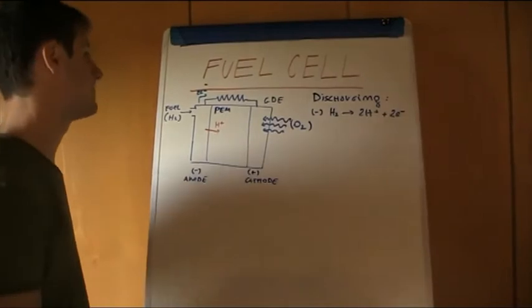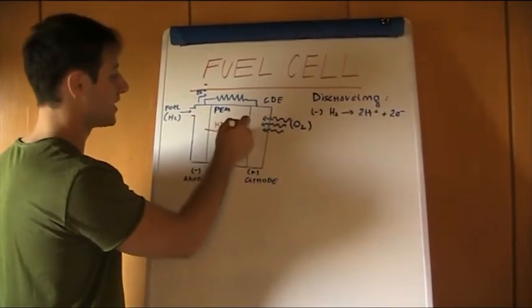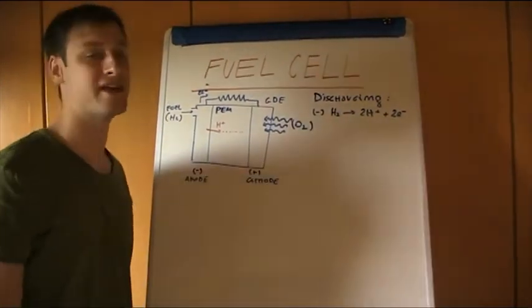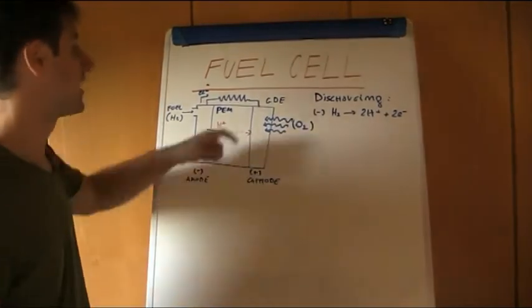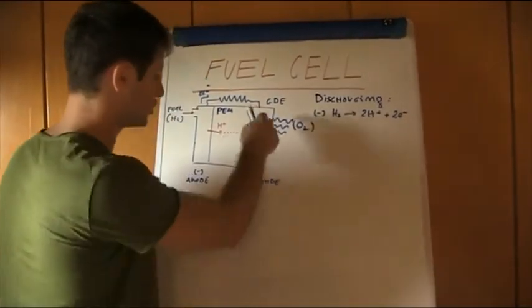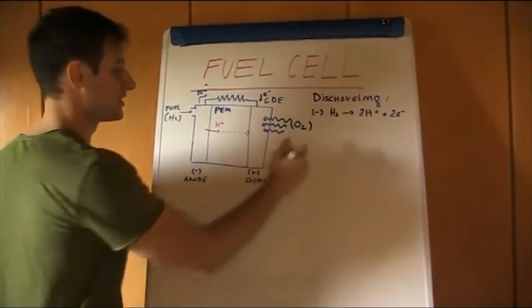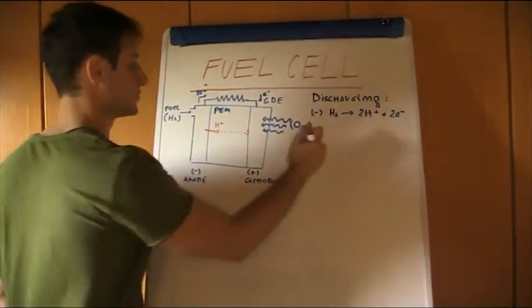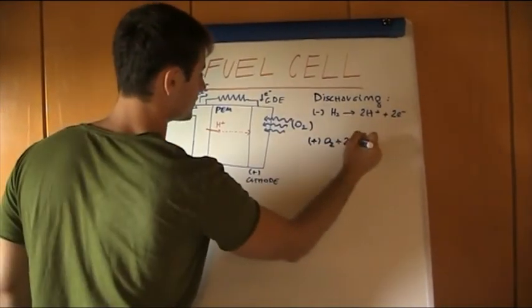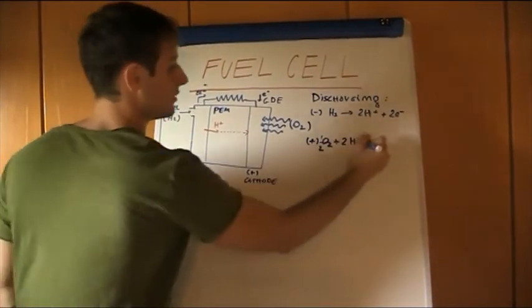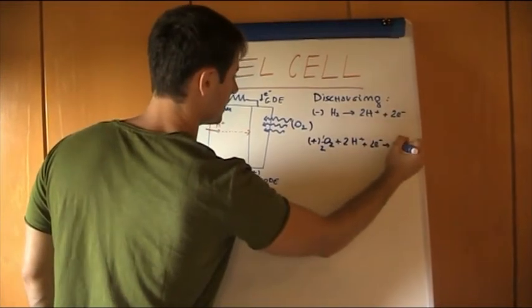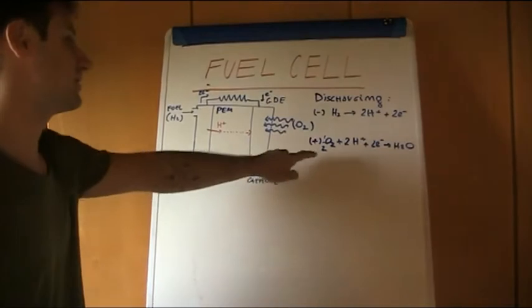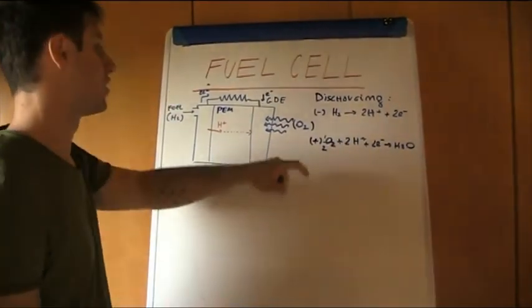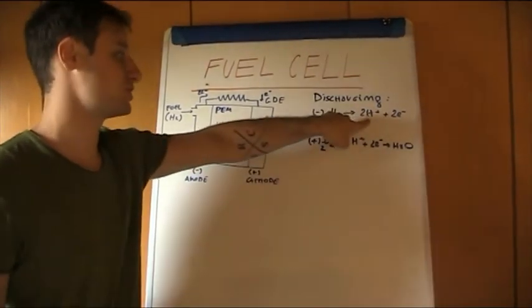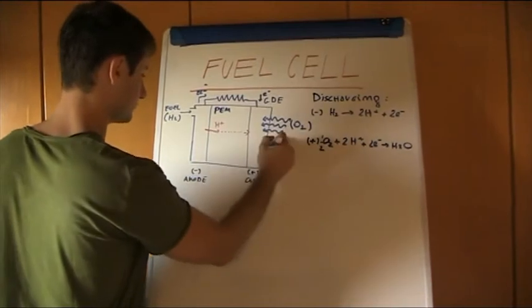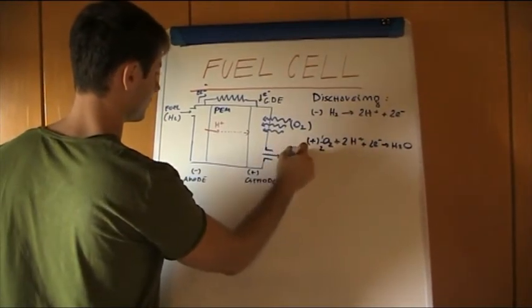But this H+ can migrate inside the proton exchange membrane due to the conductive nature of this ionomer, Nafion, and can reach, for instance, the gas diffusion electrode, where together with oxygen and the collected electrons it can react in an oxygen reduction reaction. So oxygen plus 2H+ plus 2 electrons gives water. So basically we are creating water from oxygen and the product of hydrogen oxidation. So we have here water, in acid conditions.